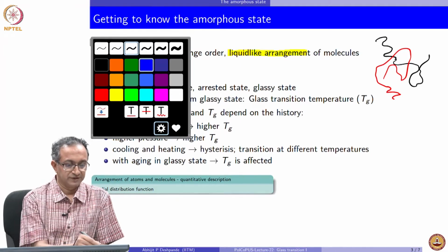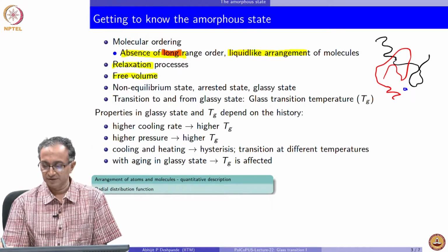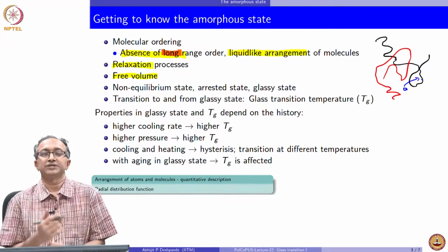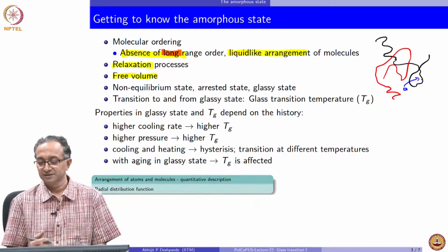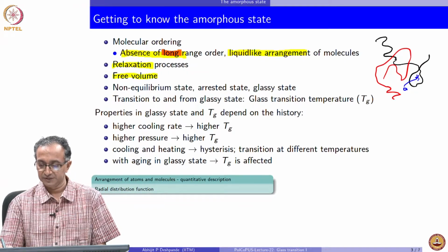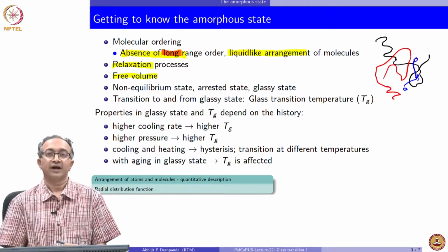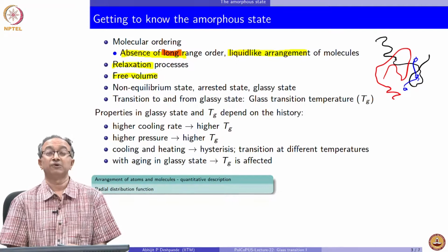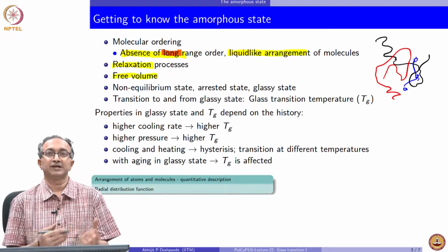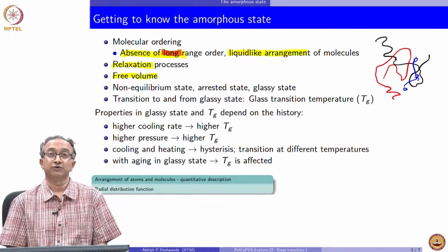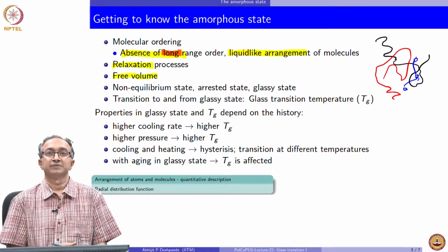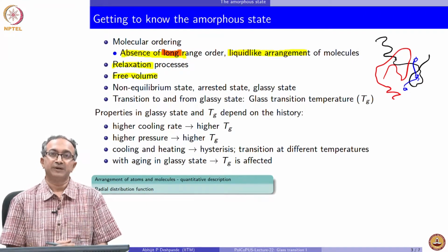For example, given that there is sufficient gap and some of these macromolecules can relax at a very slow rate, the molecule can hop across and diffuse. And so there is some free volume which is not really occupied by the macromolecule itself, which is available for motion of smaller molecules. Also the availability of free volume implies that some amount of relaxation processes can happen.